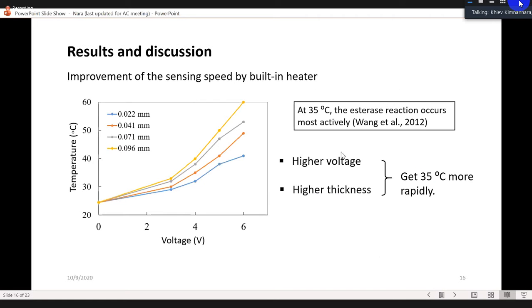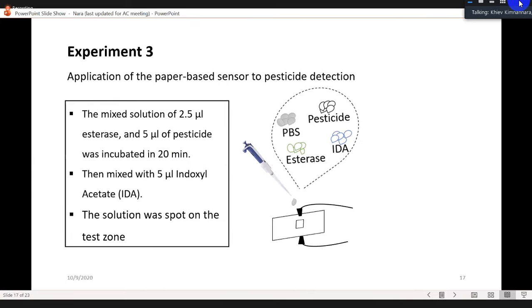So I just summarized the result from the previous slides. Based on the study of Wang in 2012, they found that at 35 degrees Celsius, the esterase reaction occurs most actively. So from the result, we can say that at higher voltage and higher thickness, we can reach a temperature of 35 degrees Celsius more rapidly. Next slide. For this slide, I apply the application for pesticide detection.